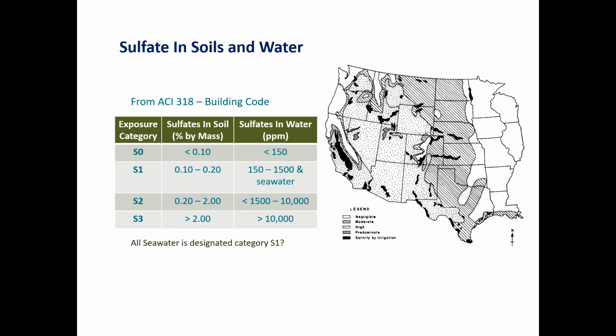So, sulfate in soils and water. We're going to look at those, and again, soils contain moisture for the most part, and obviously water contains water. So you have sulfate, you have water. So you have the first two ingredients to causing sulfate attack. So here's a simple chart from the ACI 318 building code, and it attempts to classify the severity of risk of sulfate attack. So you have 4 classes. I don't know why they didn't start with 1, but S0, I guess it just sounds like there's nothing to worry about. So S0 is exactly that. It's sulfates in the soil by percent mass that are lower than 0.1%, and in water that are less than 150 ppm, parts per million.